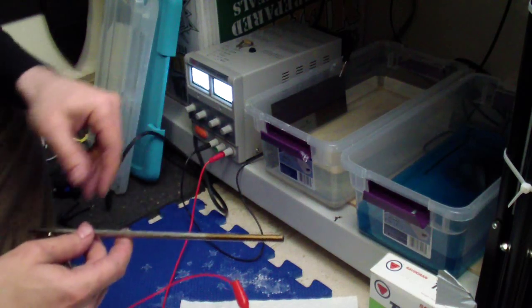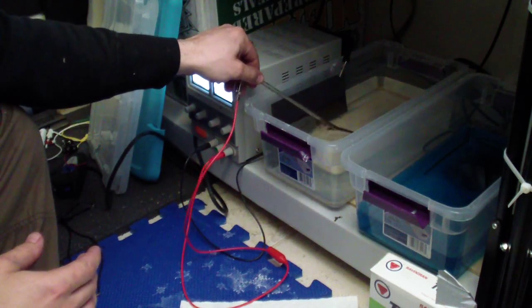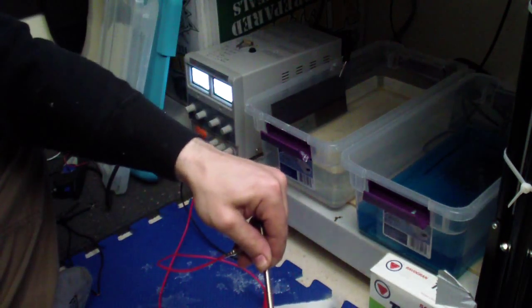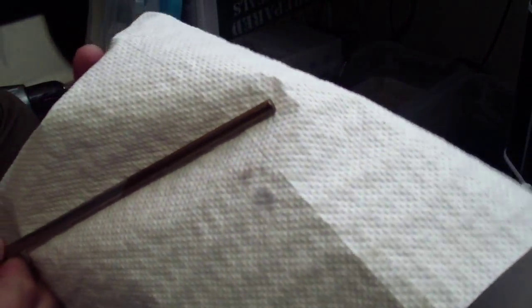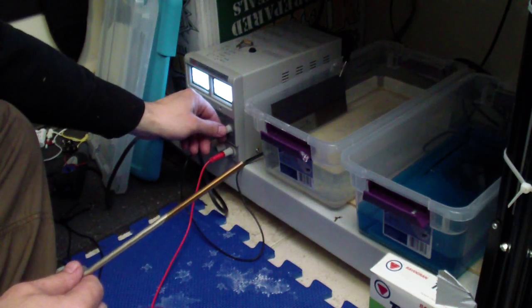Next one I have marked, this is about 16 volts. The one I came up with last time is almost like an orange with like a purple haze. I actually really like that. Some people call it bronze. There you go. Then you have like a purple around 21 volts.